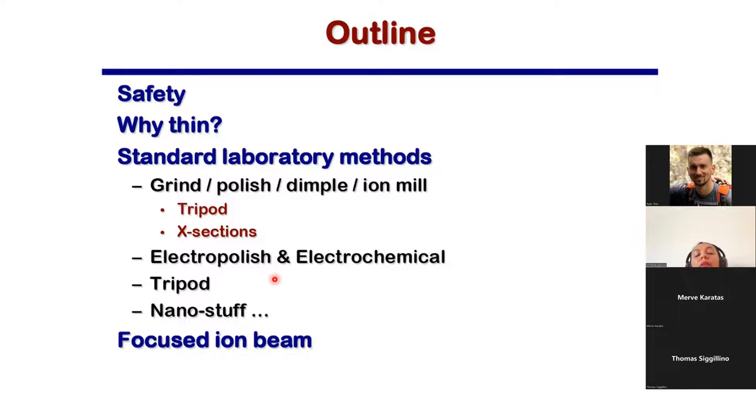A lot of students, they don't use focused ion beam, they use electropolishing. Any idea why? No FIB damage in electropolishing. Very good. Very well said.